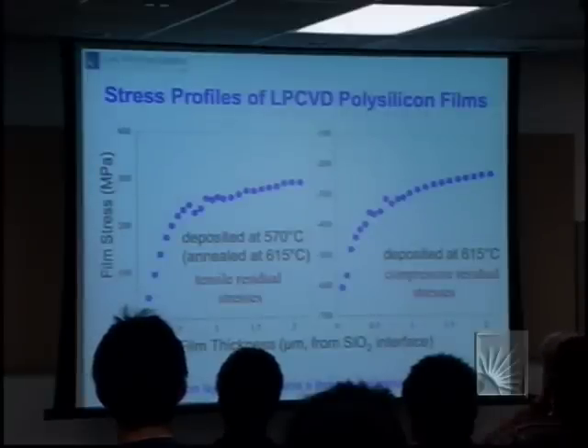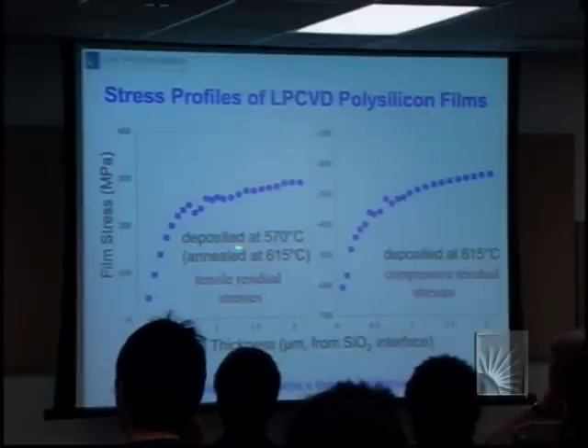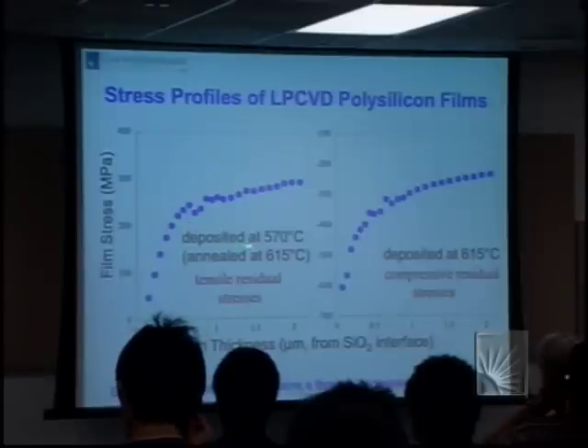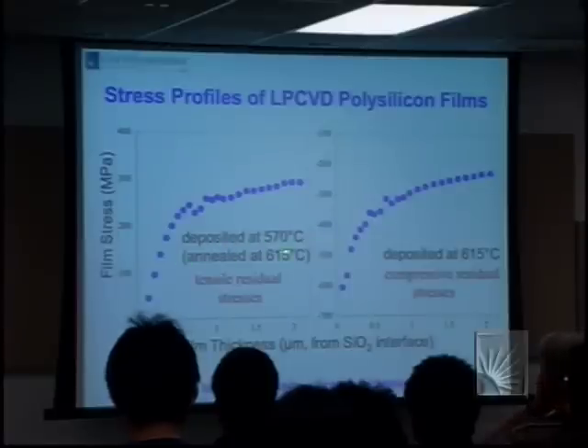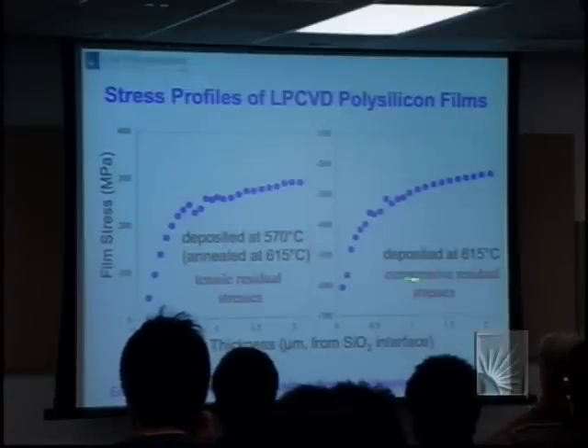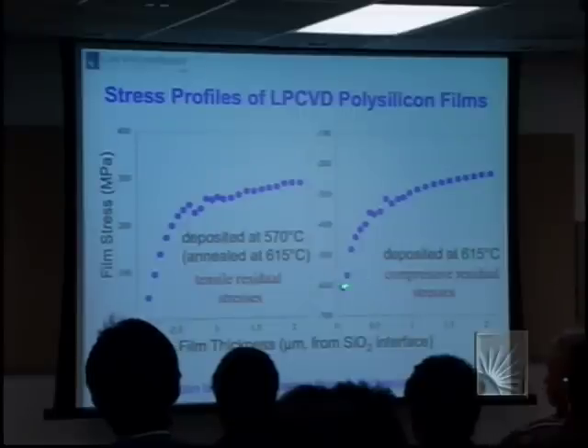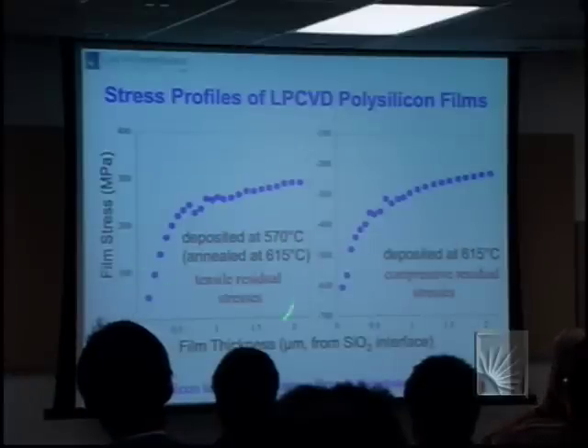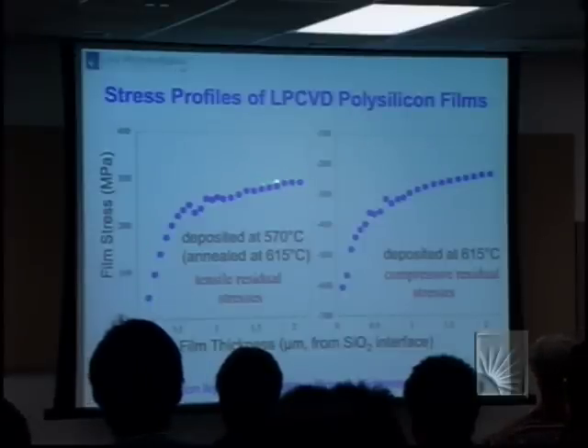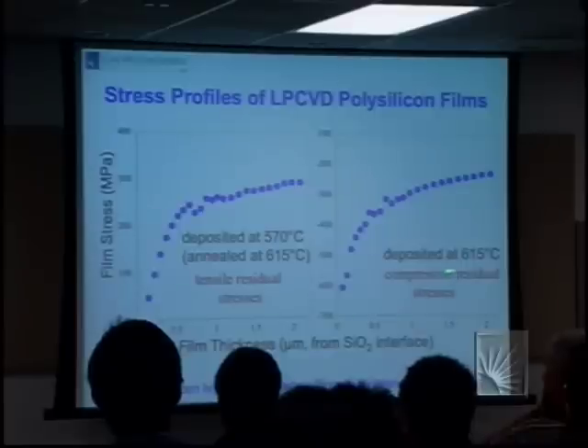Well, these are stress profiles of tensile stresses deposited samples done at a range of thicknesses, deposited at 570 and annealed to crystallize the silicon, and this for compressive stresses. You'll see that it takes a fair bit of deposition until you get a steady state. And in both cases, it's about 2 microns. It starts out that you have small residual stresses which increase to the steady state on the tensile side. Compressive stresses, the initial ones are large, and they decrease.